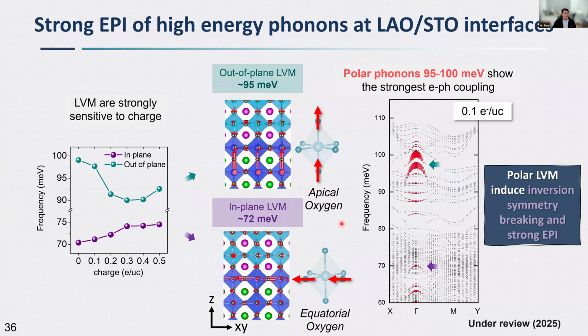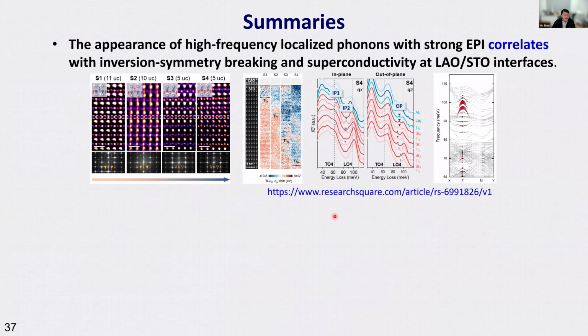So here I just give you a brief summary. We see that in this study of the LAO-STO interface, we use momentum-selective vibrational EELS, and we see the appearance of this localized high-frequency out-of-plane vibrational mode, which has very strong electron-phonon coupling, and correlates very well with the inversion symmetry breaking at the interface, and also the electronic structural reconstruction at the 2D electron gas layer. And they also correlate with the onset of the superconductivity at this optimal doping sample.